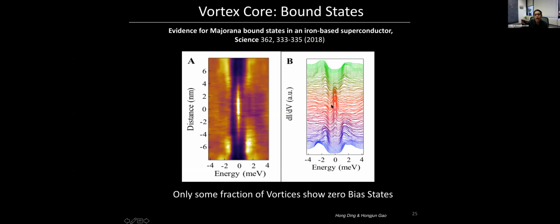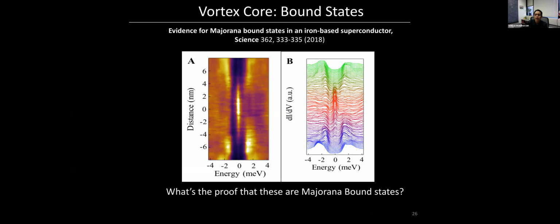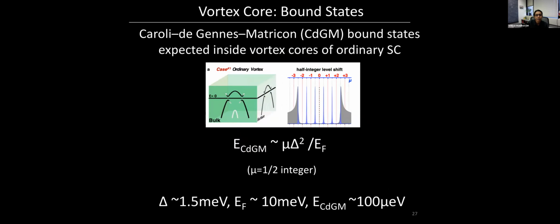They did some really nice work showing for the first time that you see the 0 bias vortex in this material. The problem is that at the beginning, when this work was done around 2018, they found that only a small fraction of the vortices would show these 0 bias states. So there was that problem. And then one can ask, okay, you can see 0 bias states. You actually see 0 bias vortex core states even in niobium diselenide. The question is, what is the proof that these are actually Majorana bound states?